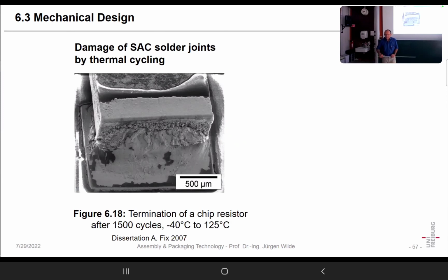Okay. What happens under much strain? That's an example. Again, Mr. Fix did his dissertation in Bosch under my supervision. And that's how a chip resistor looks after 1,500 cycles, minus 40, 125 degrees centigrade. So it looks not so reliable anymore.